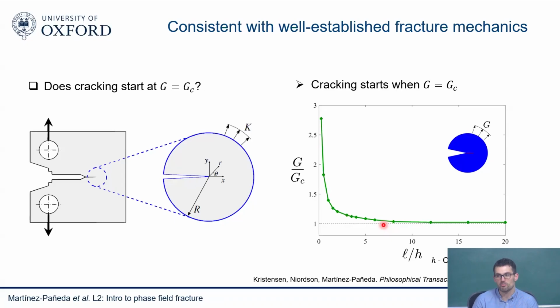In the first papers of mine and so on, people were taking 2 times, which I guess is somewhere here. It's not too bad, but I will feel a bit safer with 5 times. So you still see a lot of people in the community taking an element that is half the length scale based on those papers, but based on this type of results, I'll feel more comfortable with 5 times. And for analysis, you are actually computing L from the previous formula that you saw? Yes, I'll normally do that, yeah.